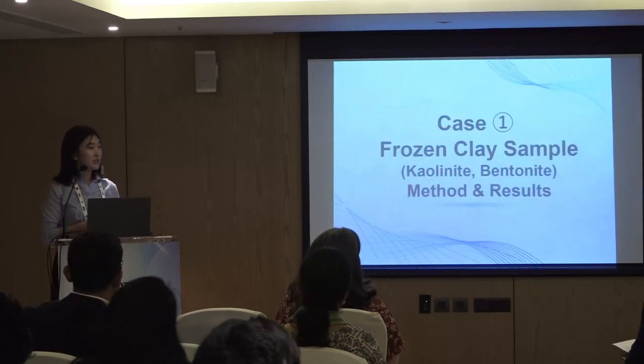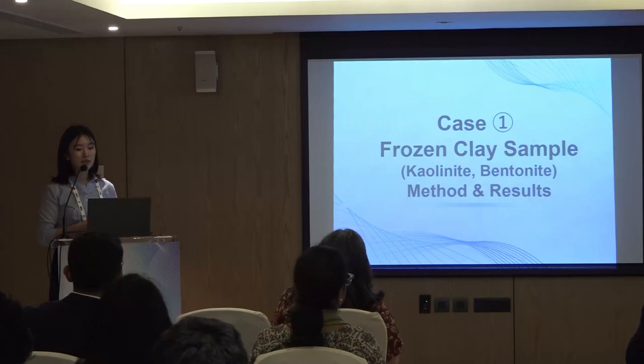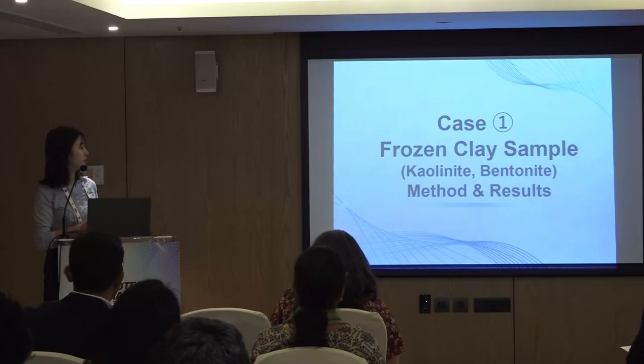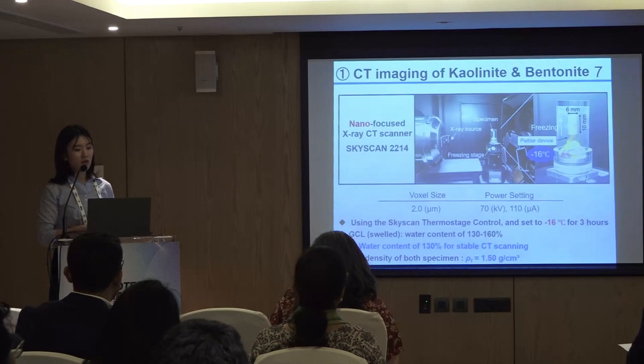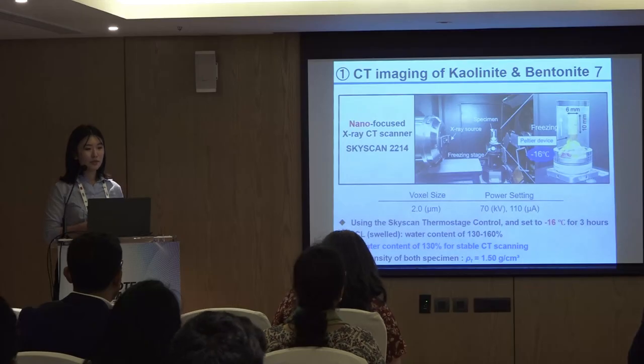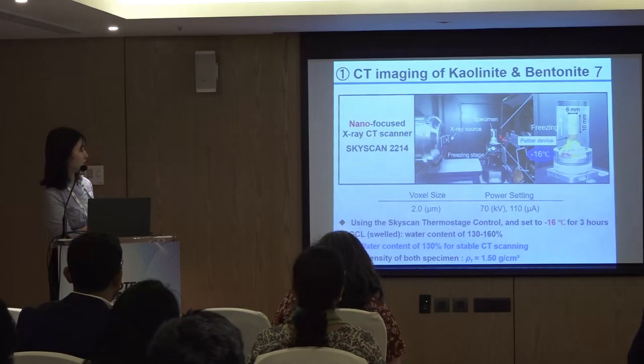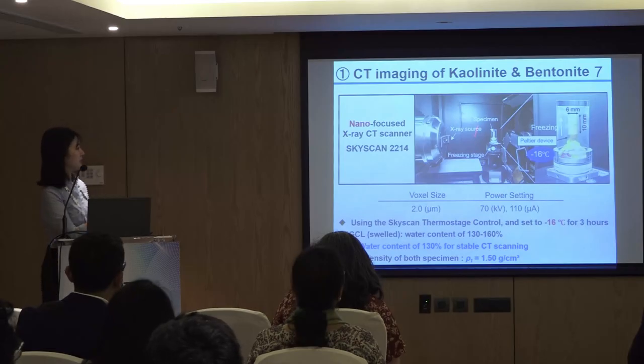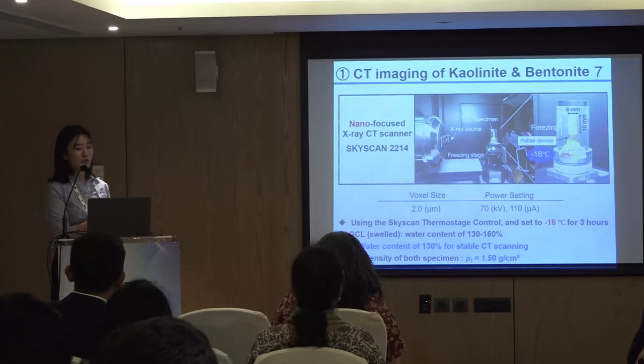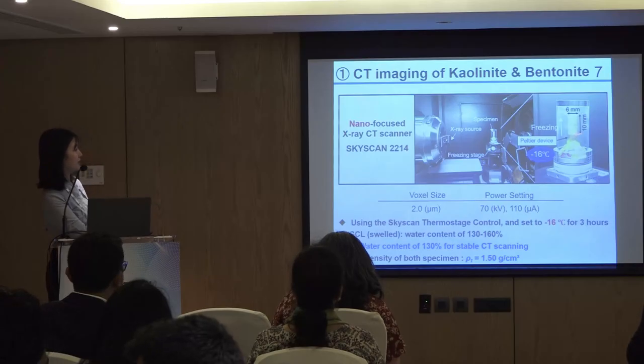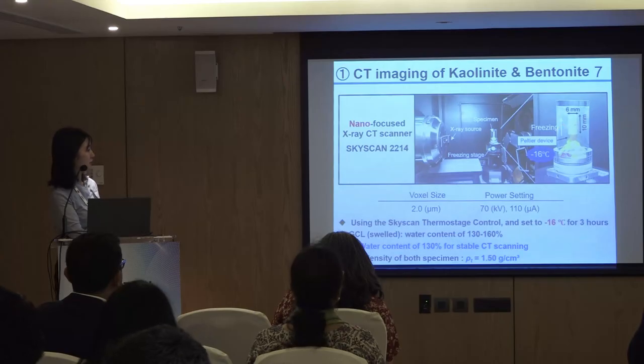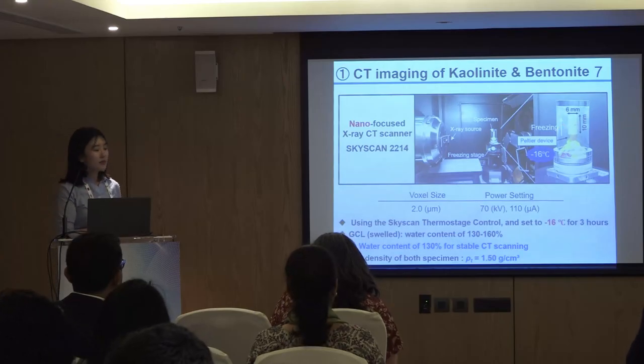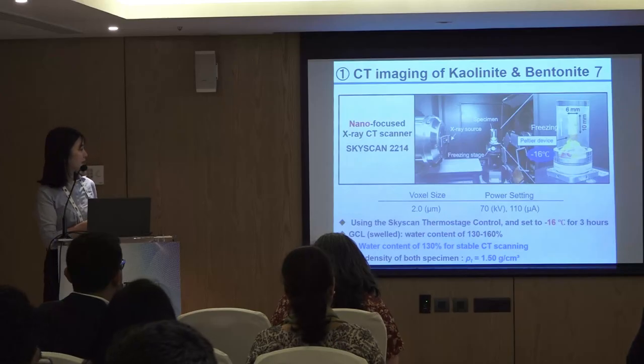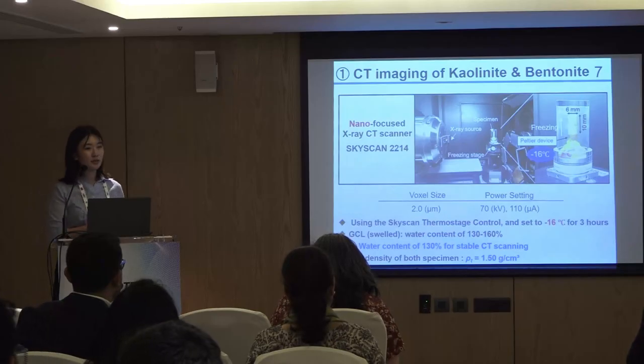Let's move on to the CT method and results. I'll start with case 1, frozen kaolinite and bentonite. This photograph shows a scene of scanning the specimen using nano X-ray CT. We put this freezing stage inside a CT scanner as shown here and controlled this Peltier element at minus 16 degrees Celsius to freeze the specimen in one direction. The water content of both kaolinite and bentonite was adjusted to 130%.